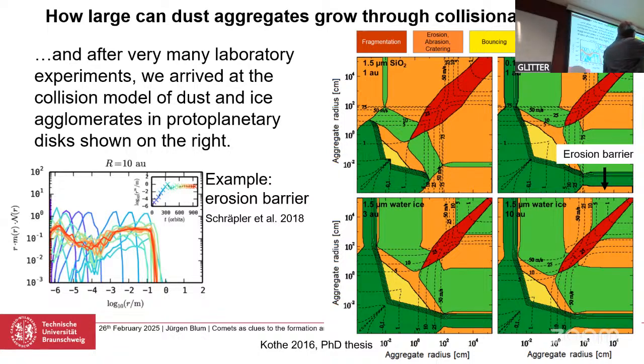So here's micron-size silica at 1 AU. Here's 100 nanometer silica at 1 AU. Here's water ice at 3 AU. Here's micron-size water ice at 10 AU. So the principal plot is the same. The contours change because there is a protoplanetary disk dust collision model behind. And the most important things are the colors here. So you're seeing greenish colors, and green means sticking. So it's good if you want to grow. You're starting in the lower left corner, you want to grow.